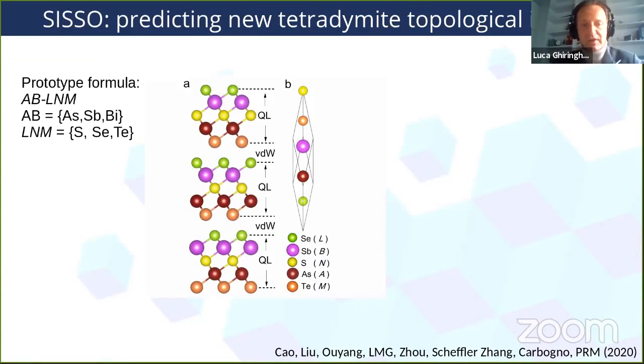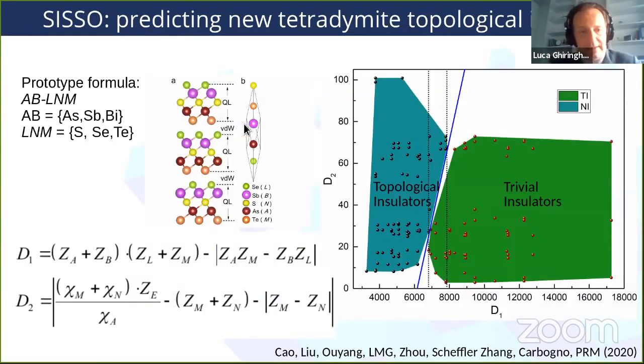This is the case of tetradymite. It's a material with this general formula, AB-LNM, where A and B could be these three elements and L, M, N could be these three elements. They form these stacked layer structures. And we were trying to see if we can predict whether these are topological insulators or trivial insulators by just looking at one of these units and then doing a kind of mixture model to model the layering. So the SISSO learning identified a very good descriptor to split perfectly between topological insulators and trivial insulators. Once you know A, B, and L, M, N, you have this descriptor on the two axes that predicts exactly whether you will form a trivial or a topological insulator.